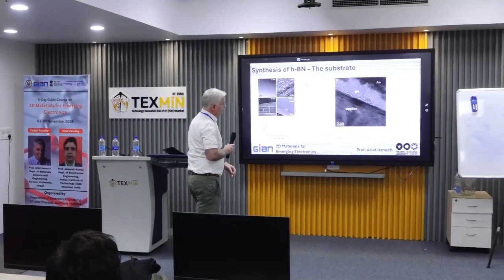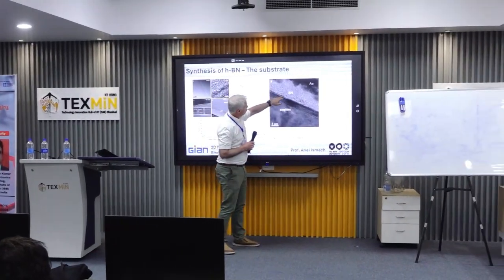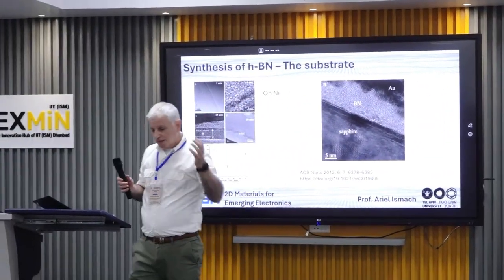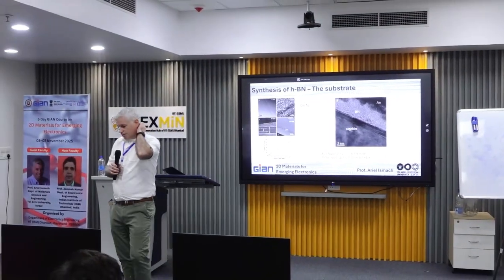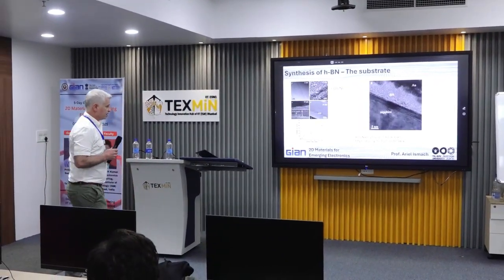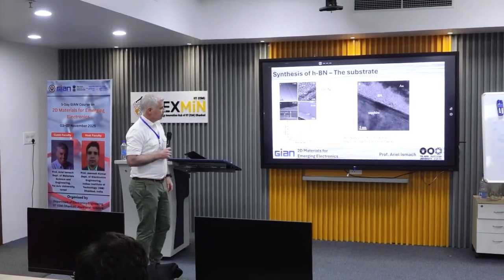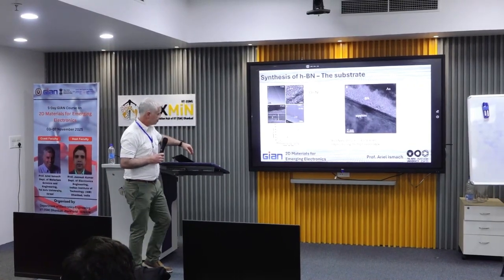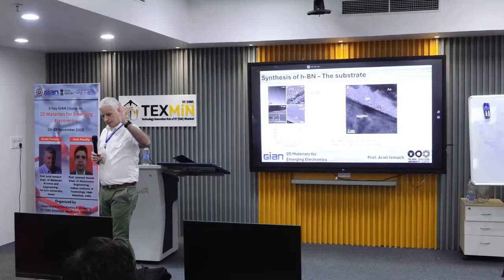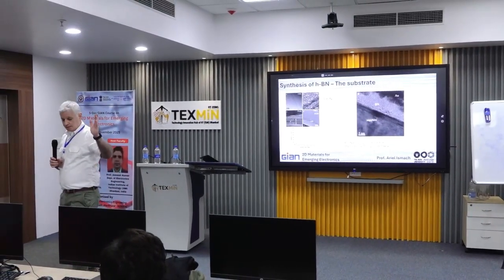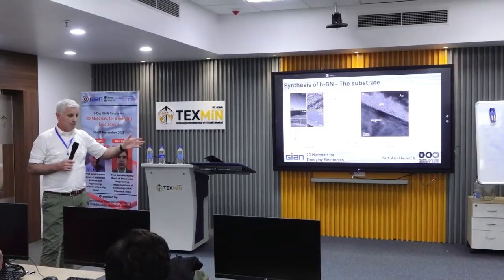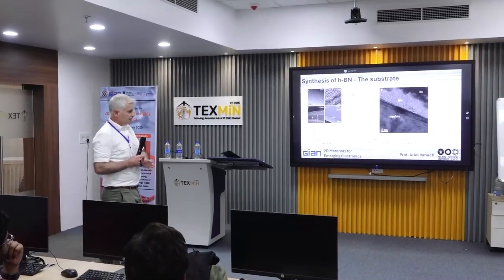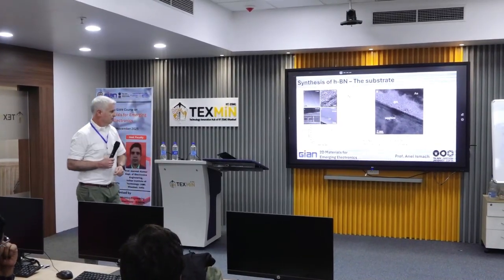And here you see that the layers are not exactly parallel, you have a lot of defects and the layers are bent, and therefore the properties of these materials are, of course, inferior to the single crystals or highly crystalline materials. So this is the synthesis on nickel, and it started with few-layer, multi-layer growth, which, by the way, is also how graphene started, with the synthesis on nickel or similar metals before copper.